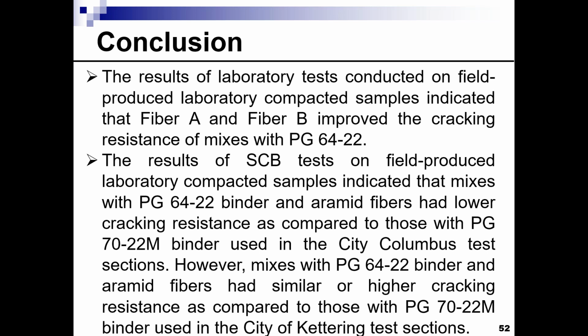The first conclusion is really that the lab testing that we have conducted on the field produced, laboratory compacted samples indicated that fiber A and fiber B improved the cracking resistance of the mixes with a PG 64-22. We have seen that basically in the city of Columbus. This was consistent in the city of Columbus.